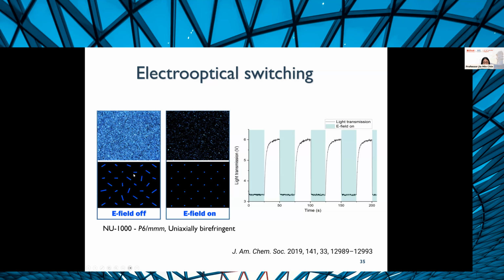When these MOFs are randomly oriented, you see a bright image because of the relatively large light transmission cross-section. However, if your particles are vertically oriented, like coming out of your monitor, then you see a darker image. So we can follow this by attaching a photodetector to the optical microscope, hooking that up to an oscilloscope, and plotting the graph. We see that when the E field is on, you get a dark image, so low light transmission. But if you turn it off, you have relaxation, and it goes up to a brighter image. Once you turn the E field on, you get a very fast response, a drop in the light transmission. That response time is about 0.1 second, although it could in reality be lower, because that was the limitation of what we could observe with our instruments. And here is a little video of what you actually observe under the optical microscope.